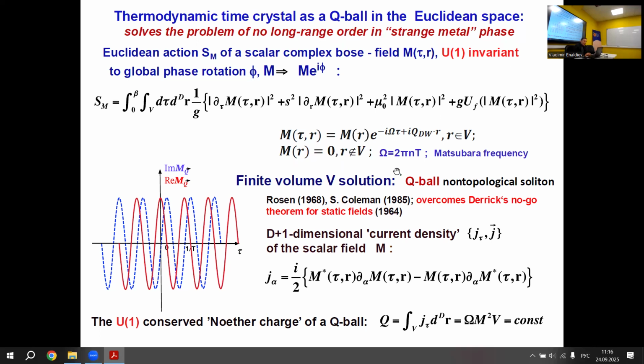And so this soliton was then called QBall. So it means that there is no long range deformation in the crystal, or if it is not a deformation, people consider also exchange between electrons with spin waves, spin density waves. So we don't need long range antiferromagnetic order as we know is present in cuprates before they become superconductors. So here we have only short range order, and this could be either charge density wave or spin density wave with finite size.